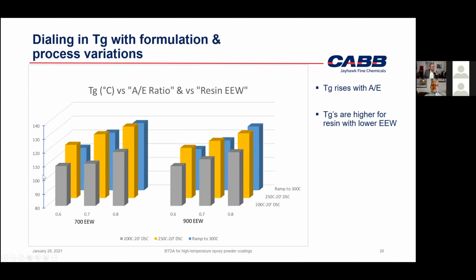And then, of course, if you compare broadly this 700 equivalent weight data with the 900, you can see that the Tgs are slightly lower for the 900 resin, which makes sense. When you go to 900, the space between the epoxides increases within the structure of the resin. So you have overall reduced cross-link density in the three-dimensional network. So that makes sense. And this coating is not necessarily worse. It could be the right coating for that application because you may need to take a little bit of the edge off of the rigidity that a lower molecular weight will give you.